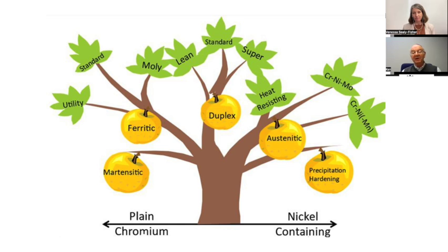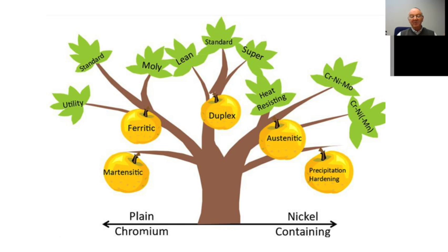They can be used in cryogenic applications, and also they have very useful forming and machining characteristics. Their weldability is good, and hence they're useful. They're very utilitarian, and especially around the 304, 316 type compositions. Now, the problem with the 304, 316 type compositions is that they are very susceptible to chloride stress corrosion cracking. So remember, we said on the one hand, the ferritics were immune to it. On the other hand, the austenitics are susceptible to it.